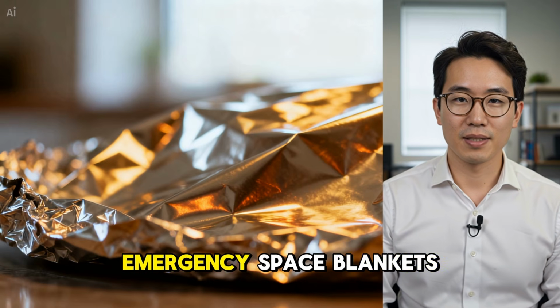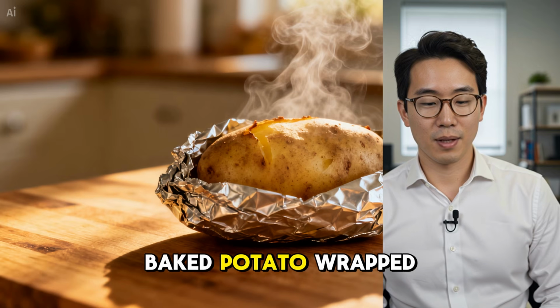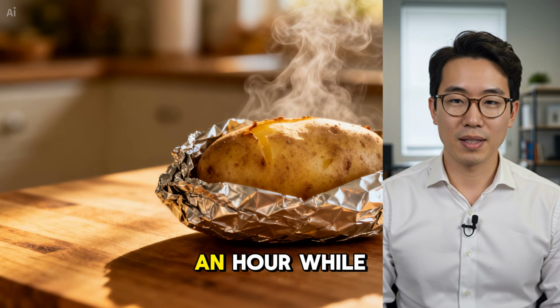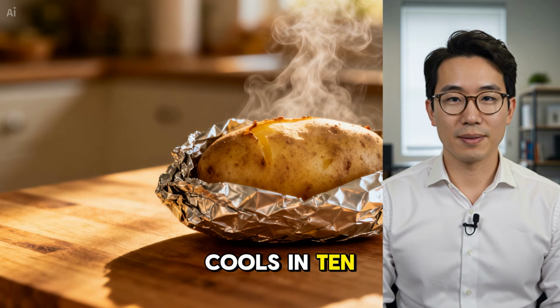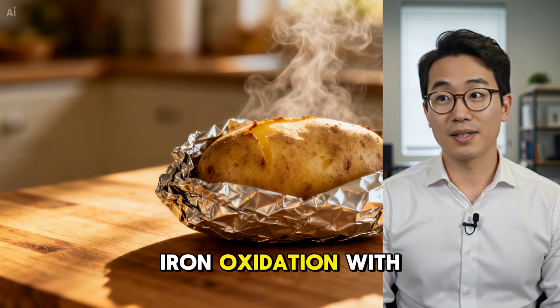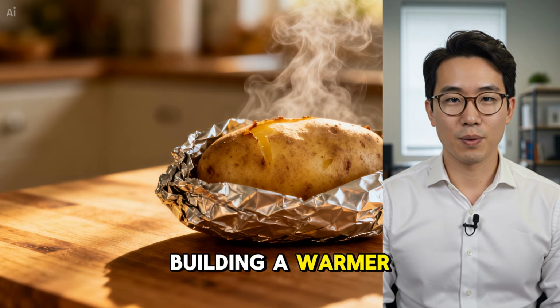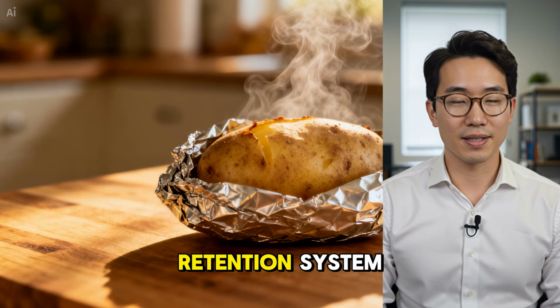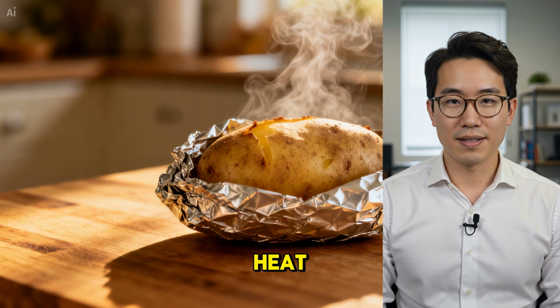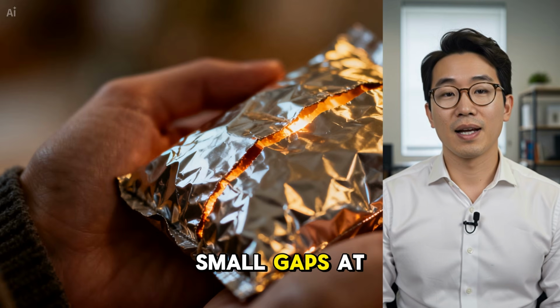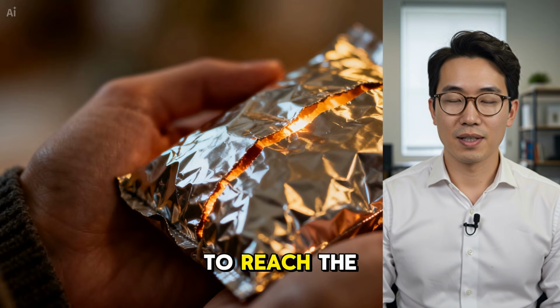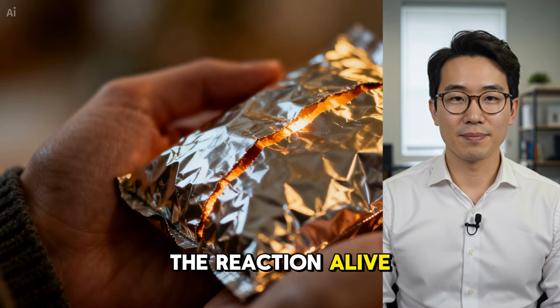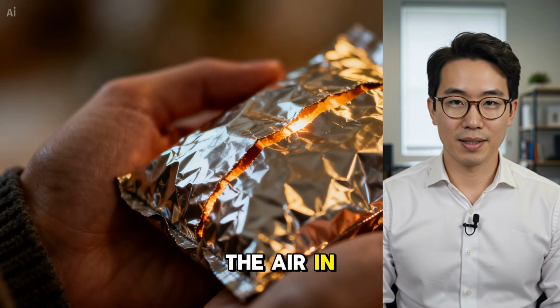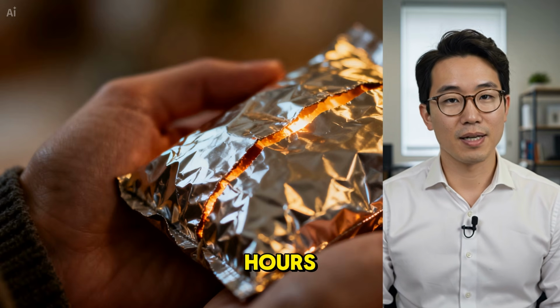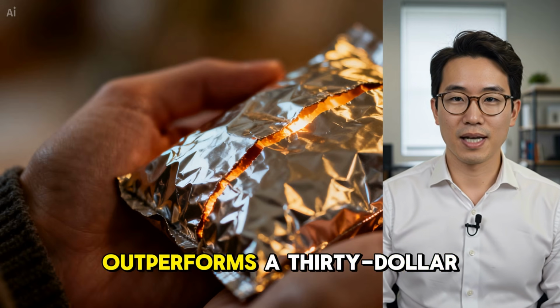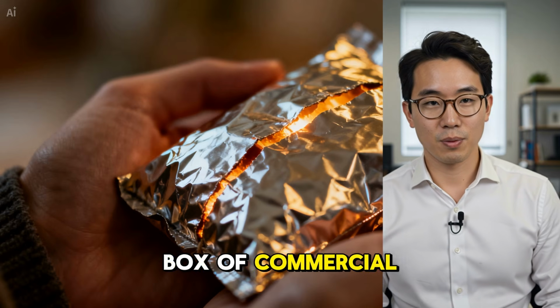Same physics behind emergency space blankets. Same reason a baked potato wrapped in foil stays hot on a counter for over an hour, while an unwrapped one cools in 10 minutes. When you combine iron oxidation with aluminum foil, you are not building a warmer. You are building a directional heat retention system. The chemistry generates heat. The foil concentrates it. Small gaps at the seams allow just enough oxygen to reach the iron and keep the reaction alive. Heat that would otherwise bleed into the air in minutes is held against you for hours. A complete heat source for under $1 that outperforms a $30 box of commercial warmers.